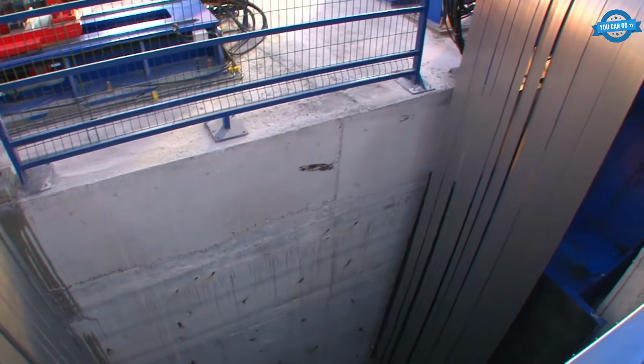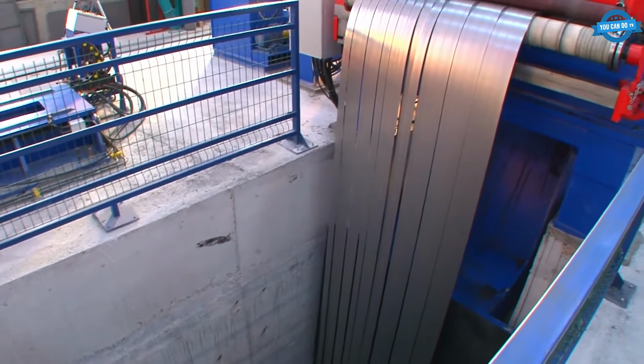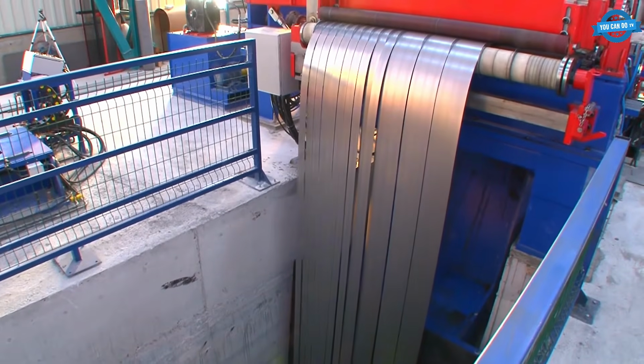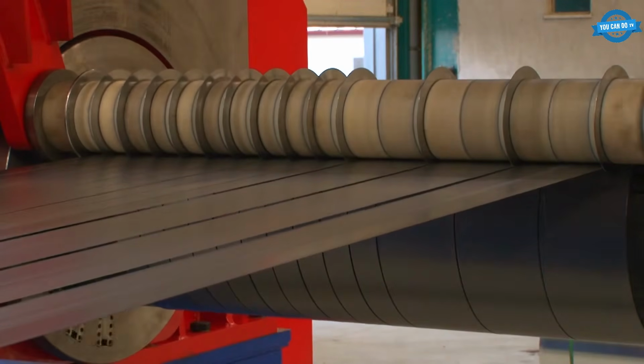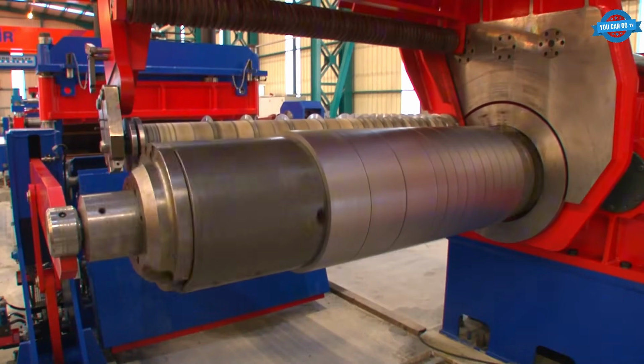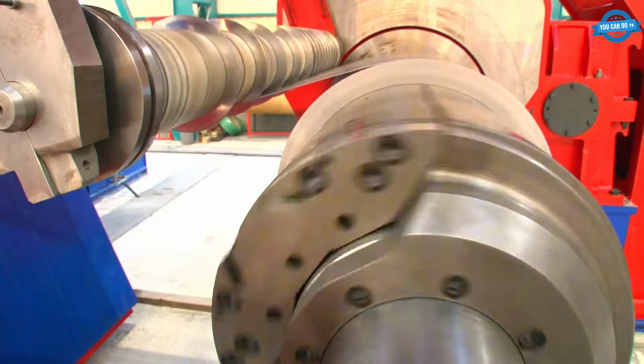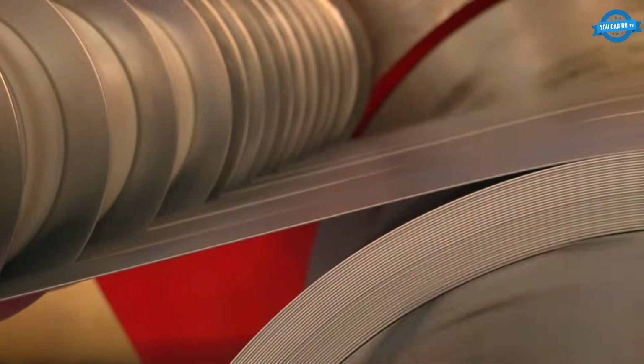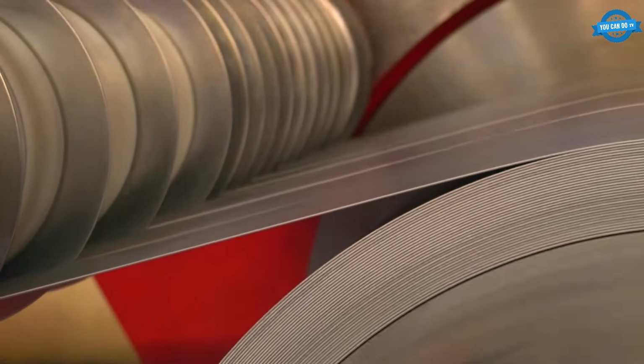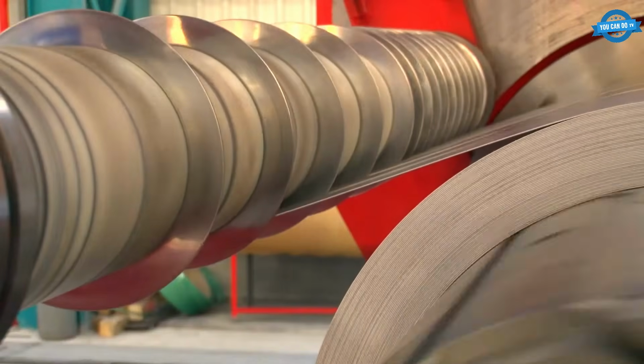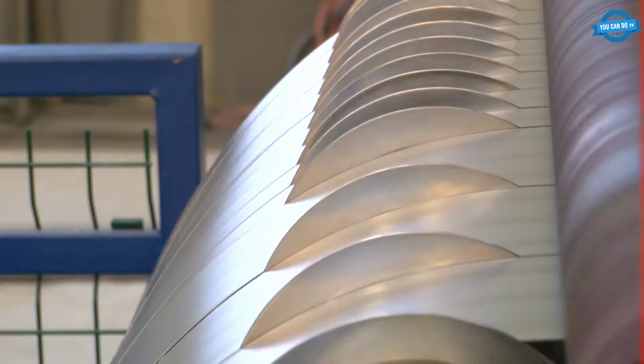On this line, 1,650 millimeter wide steel gets cut into strips as narrow as the downstream press needs. The tolerances matter more than they look. A slitting line running out of alignment leaves burrs on the edge, and burrs jam a stamping die within a shift. 6,500 tons on one press!